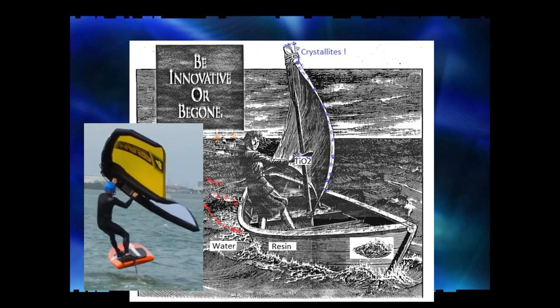Now, in our journey to try and find the right resin, the right TiO2, we have to think beyond the bounds of where we are. And I will tell you right now, as of 2020, the resins are changing dramatically. The resins no longer have emulsion surfactants. The titanium dioxide no longer has a dispersant. There's reactive polymers that are going down on the surface of the titanium dioxide, and the paint is becoming a reactor. And that means that there is nothing to weep into the water.